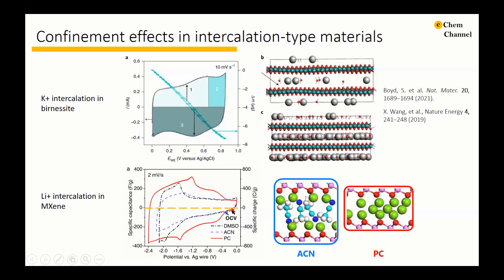2D transition metal carbide MXene is also a typical pseudo-capacitive material. However, the co-intercalation of organic solvents with lithium into Ti3C2 will reduce the total charge storage capacity. When acetonitrile is used as a solvent, the acetonitrile molecule is present in the interlayer and the pseudo-capacitance is weakened compared to using propylene carbonate as the solvent. Hence, the interlayer space and environment determine the charge storage characteristics for intercalation processes of layered materials.